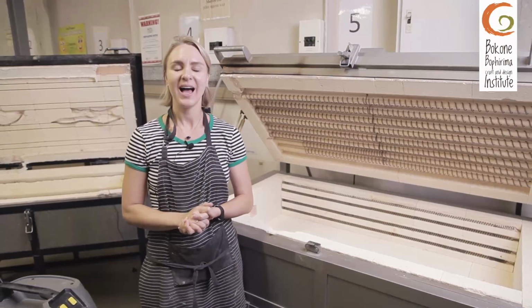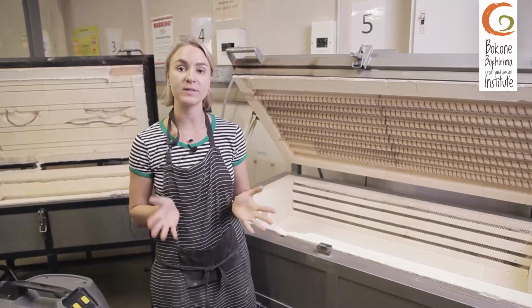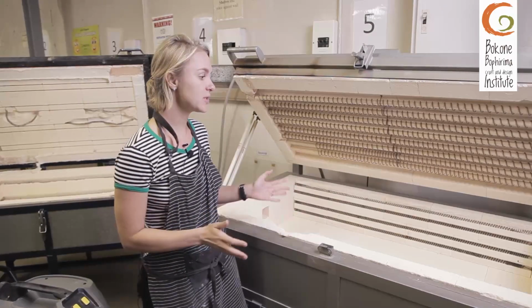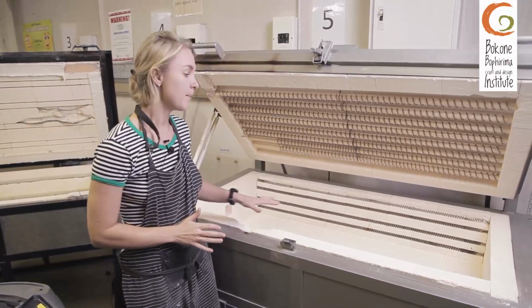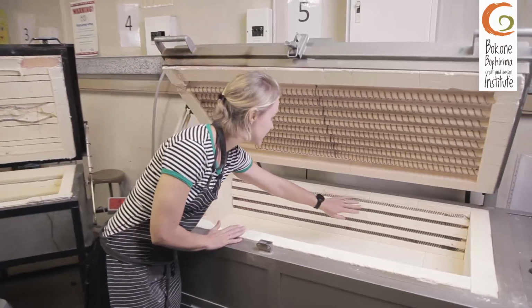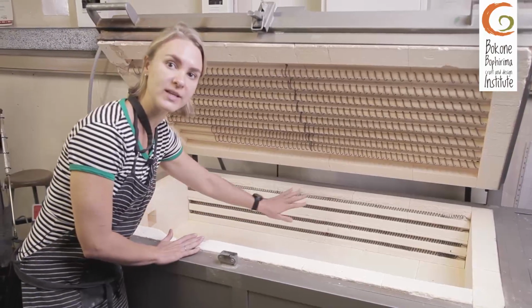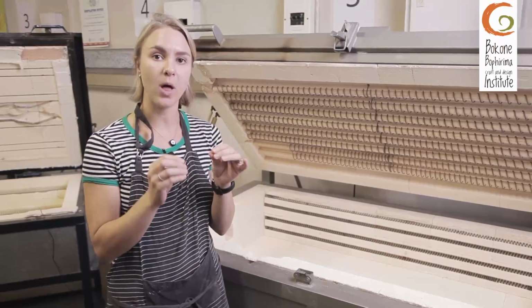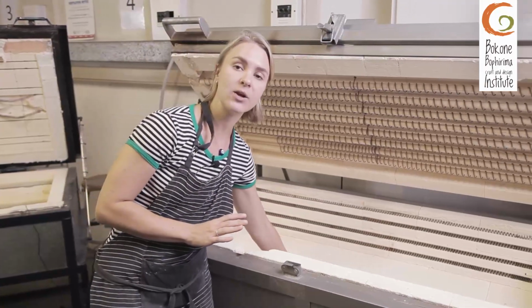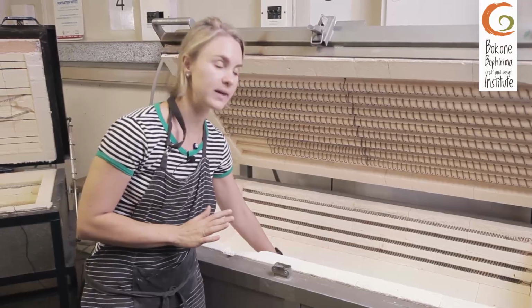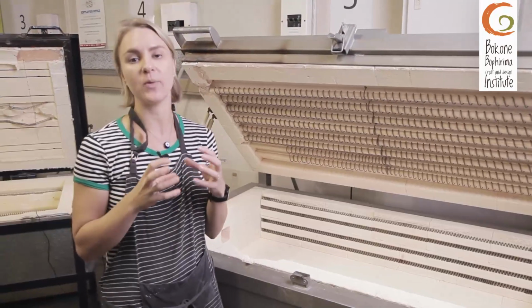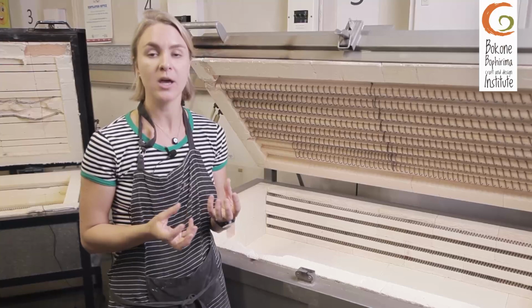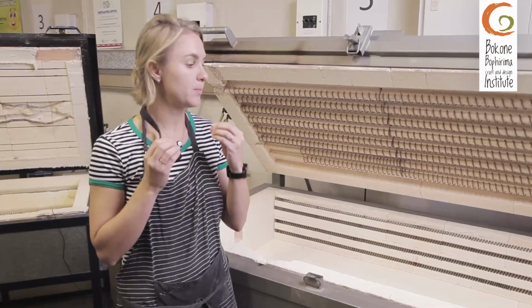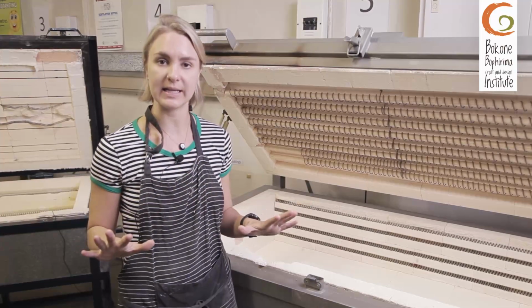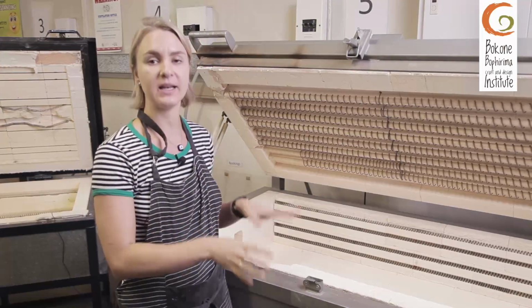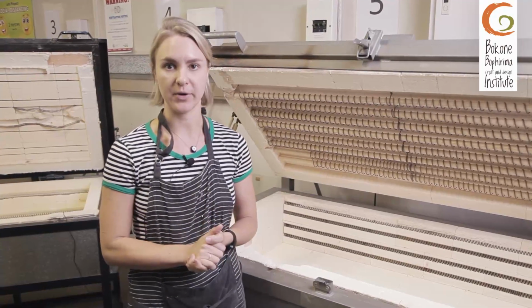Okay. Hi everyone, I'm going to explain to you now the importance of prepping your kiln. One needs to ensure that the kiln is completely clean by vacuuming the inside, as well as going lightly over the elements to ensure that no dust or leftover plaster is sitting on the kiln elements or on the kiln bricks, as this dust can create devitrification again in our glass. So with glass, it's always important to make sure that the area is completely clean before putting our kiln shelf in and our glass in and switching the kiln program on.